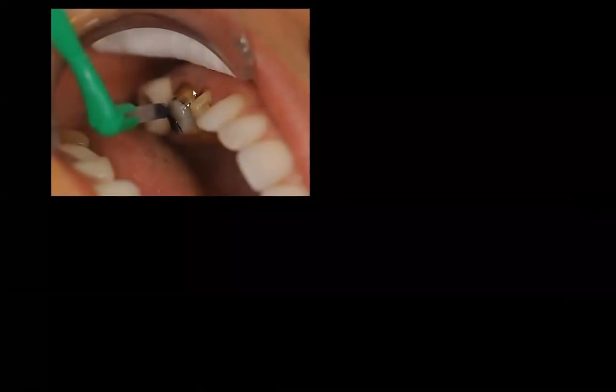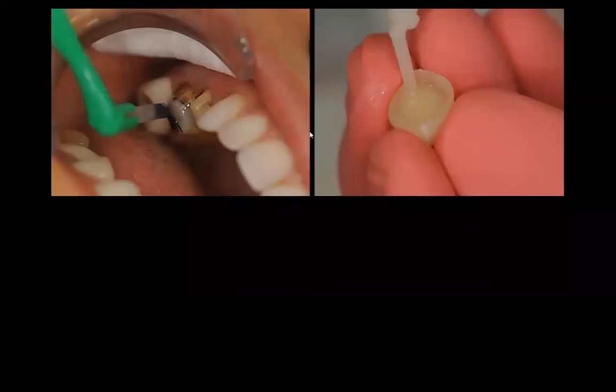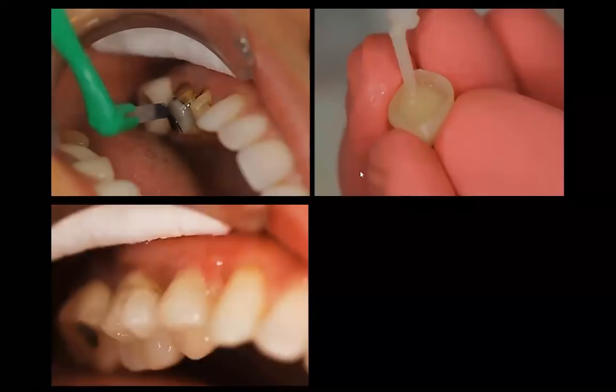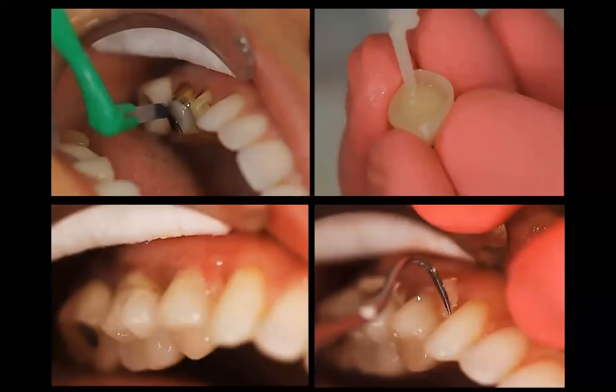So here we are with our universal adhesive, because I used to bond all lithium disilicate in, even if I didn't need to. I just felt better because it was glass bonding it in. So they treated them that way. So here we are, we're filling our crown up. And here it is in the gel state, flash cure in the gel state. And I come in here with my scaler explorer, whatever, and I just clean that off, floss the contacts, bite on a cotton roll, wait 2 to 3 minutes, light cure, and then adjust occlusion and polish. That's how we do it.